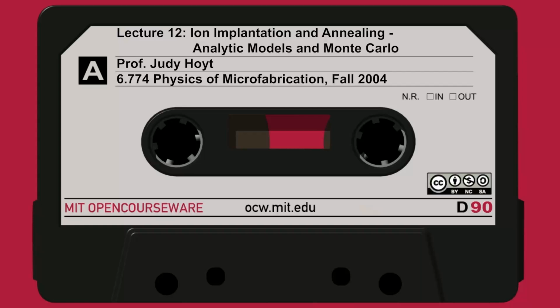There's one last term here, which I circled, which is the electronic charge Q times phi, where phi is the dose of a dopant that's ion implanted into the surface of the wafer, divided by COX. So this extra term isn't here unless you do an ion implant, but that extra term can be added in, and if you can very precisely control phi, the dose, then you can very precisely control the threshold voltage and set it to a level that you need.